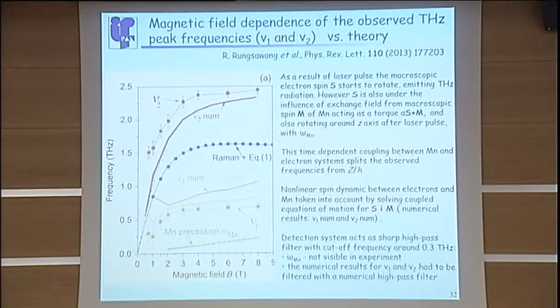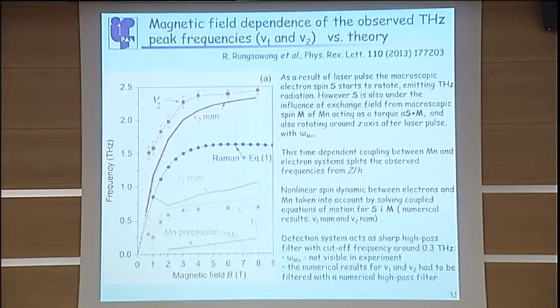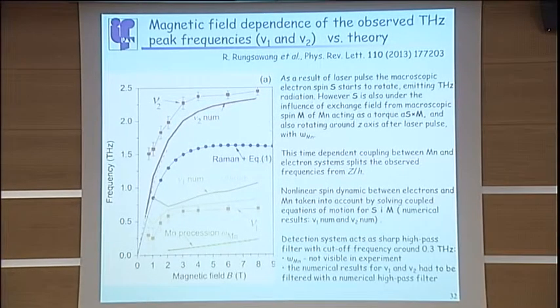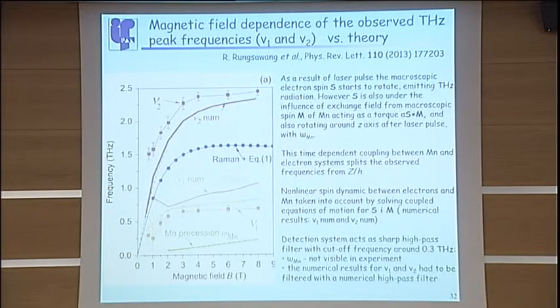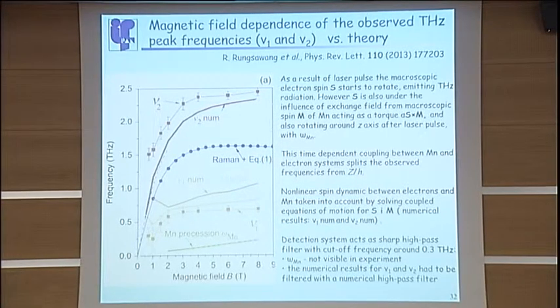As a result of the laser pulse, the macroscopic electron spin starts to rotate in this in-plane magnetic field and emits terahertz radiation in the relaxation time. But this spin is also under the influence of the manganese macroscopic spin, which also rotates around this magnetic field. This manganese spin acts on S as a torque, and this produces the splitting into two frequencies. You can compare experimental data, which are for nu 2 given here and nu 1 given here. Our colleagues had to solve numerically the coupled equations of motion for S and M, and the numerical results are presented here, nu 2 numerical and nu 1 numerical.